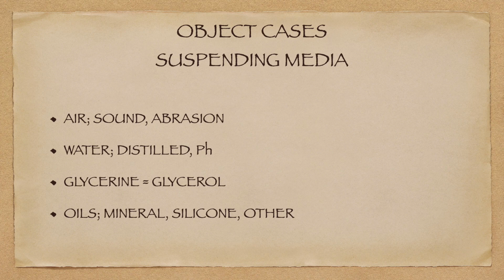However, glycerol is very much so, and so that's why it was mentioned earlier not to use that in acrylic object cases. It tends to absorb water through the plastic material, diluting itself but increasing the volume and then increasing the pressure within the object case, causing failure over a period of time.